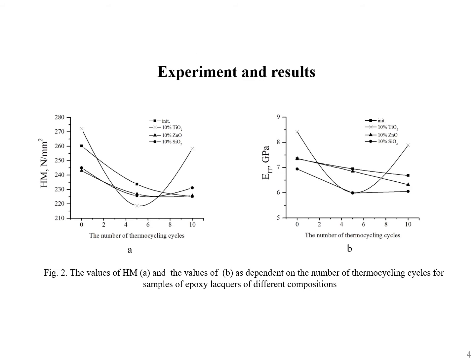Originally, we obtained mechanical characteristics for the coatings in the initial state, not subjected to thermal effects. A load of 1 newton and a loading time of 40 seconds were selected as the loading parameters. The values of Martens hardness and the normal elastic modulus for the unmodified lacquer coating amount to 260 newton per square millimeter and 7.3 gigapascal respectively.